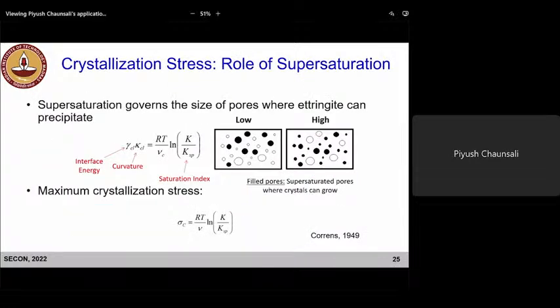So this supersaturation affects the size of pores where crystals can precipitate. In this case, ettringite, because we know that the ye'elimite hydration in presence of gypsum forms ettringite. And this is the crystal. So the point is, what you see here, two images. One is the case of low supersaturation, one is the case of high supersaturation. And this is the relationship between the curvature where the crystals can grow versus saturation index, a measure of supersaturation. The point is, if the degree of supersaturation is high, that means the crystal can grow in smaller pores, right?